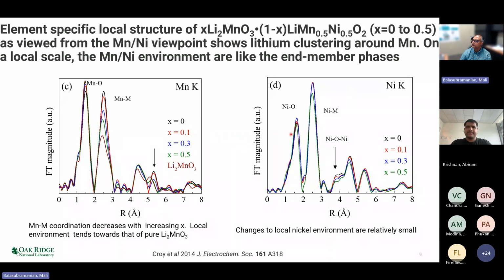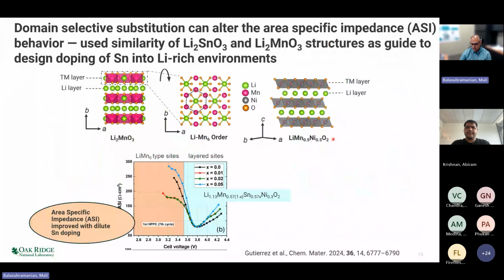And you can come to the same conclusion that the nickel, on the other hand, has a full complement of 6 neighbors, and as you change X from 0 to 0.5, the changes on nickel are much smaller than what you see in manganese, again showing that the lithium clustering is predominantly around the manganese. So these are the kinds of things that you can understand about the average structure in a very element-specific manner, which is harder to perceive in X-ray diffraction.